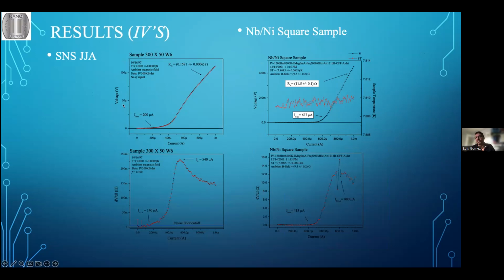This curve is the current-voltage characteristic. I send an increasing current between the two leads of the sample, and I measure the voltage using that technique I was telling you about, where you switch the voltage polarity back and forth, and that removes the voltage drop on the leads. So you start sending current. There will be a region where there is no voltage drop. The voltage is zero, so that's fully superconducting, and that gives me a measurement of the critical current. The critical current is the current that we can pass through the system without having any voltage drop, where the resistance is zero. Above the critical current, a voltage appears across the sample.